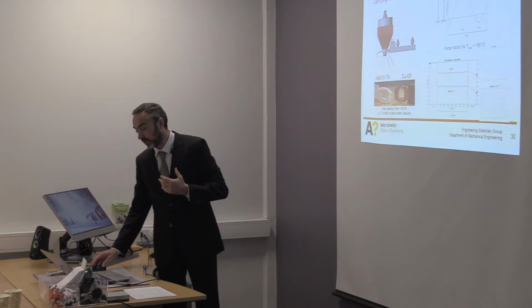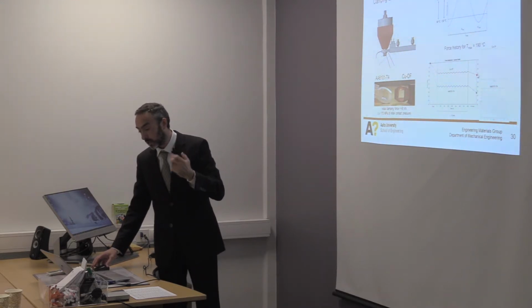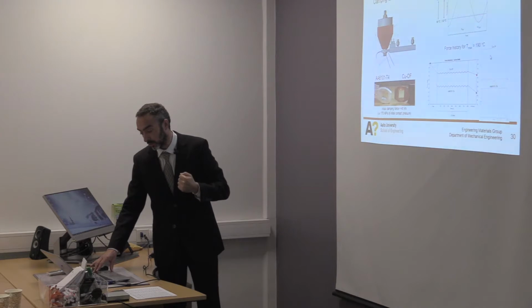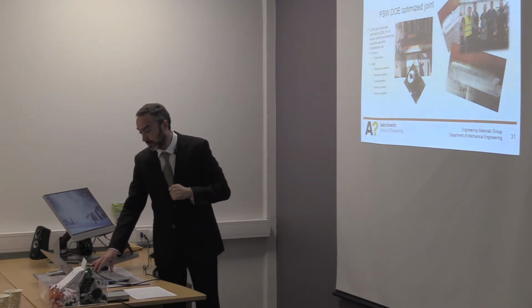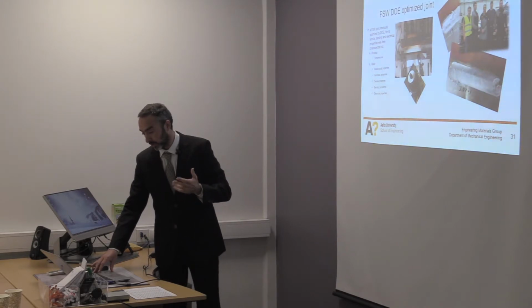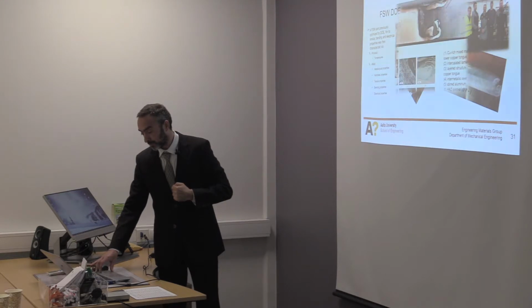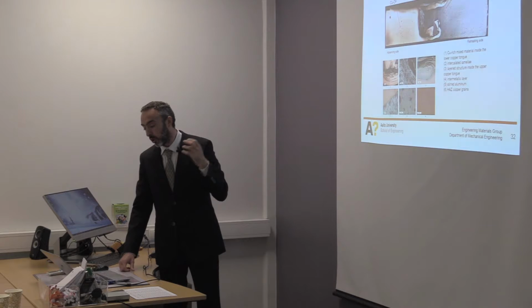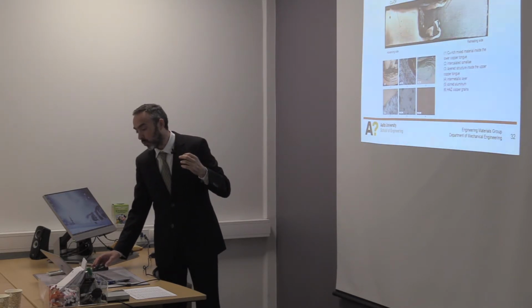And we found that the force relaxation at the tip when we use copper or aluminium is quite different, with a life in terms of retaining the clamping force double that of aluminium. So it's quite important, and the investment has a big return immediately on the maintenance of these bus bar connections. Here you can see the team that implemented this work, also sponsored and oriented by Promeco, a company in Finland. The very important profile is mechanical clamping with chemical joining activation all around the joint. We can go into detail on this.